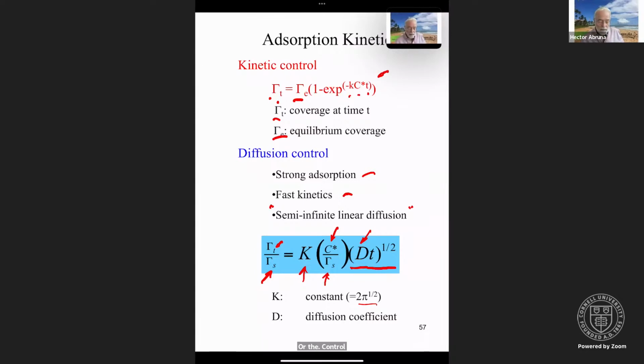One can do two experiments and basically figure out whether the process is kinetically controlled or diffusion controlled. And what would that be? Let's say I have a surface, I have some solution species. One way to change mass transport is to stir the solution. So I look at the adsorption kinetics, I measure the coverage as a function of time, and then I stir the solution. If it changes, that means I'm diffusion controlled. If it doesn't change, I'm kinetically controlled. And then you can do the appropriate analysis. But that's a very simple way of telling which one is controlling, whether it's kinetic or diffusion control.